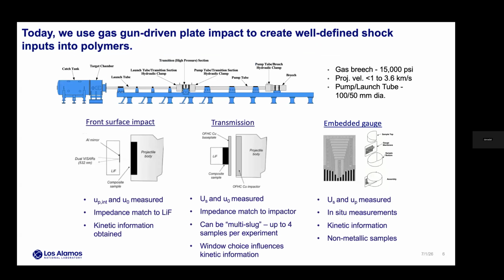Today we do a lot of experiments with either gas gun drive or laser drive, and so our diagnostics are far better as far as measurement of the wave going into the material and the shock waves coming out of the material. And we can do a whole variety of different experiments, such as shock release experiments or even embedded gauge experiments, where we can follow the shock-driven flow as a function of time and position. So I just show a picture here of our two-stage gas gun at Los Alamos. It's a large bore two-stage, and we are able to do a variety of different experimental geometries to study polymers.